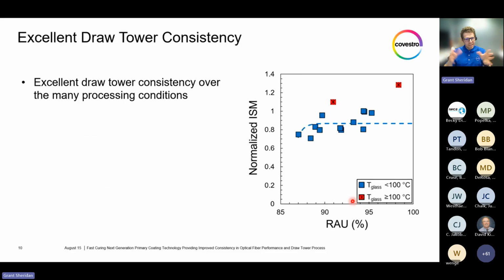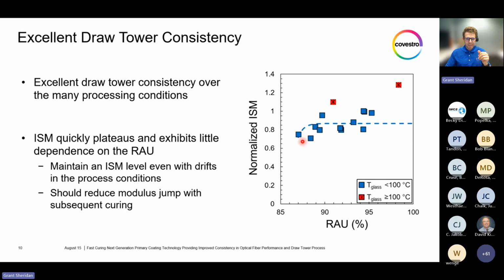Just like we did with the DTS data, we're looking at the draw tower consistency on this actual draw tower at the Nextrom R&D Center. So we have the normalized in situ modulus versus the RAU. As we can see, once again, we see very excellent draw tower consistency over all the processing conditions, all the draw speeds, all the fiber temperatures, where the in situ modulus quickly plateaus and is exhibiting more insensitivity to the RAU as our current technology had shown on the DTS. This enables maintaining an in situ modulus level, even with small drifts in process conditions, and should reduce the modulus jump with subsequent curing.